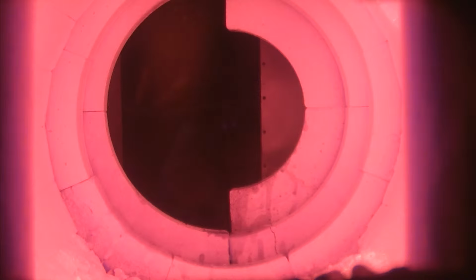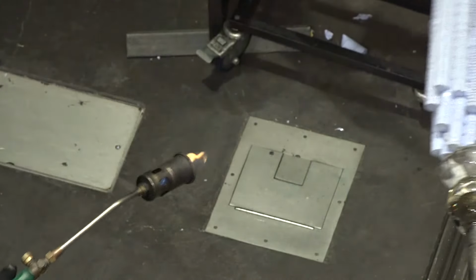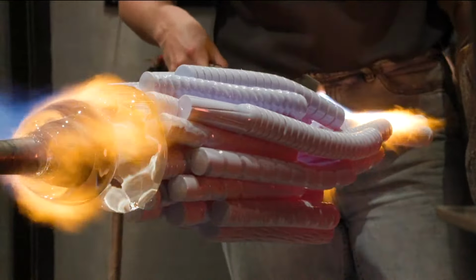So when glass heats up, it expands, and when it cools, it contracts. If it happens really quickly, the glass will crack and break. So if it heats up too quickly or cools down too quickly, stress will form in the glass, and it will come out in the form of cracks. You don't want your glass to crack. And so in order to get these really thick pieces down to room temperature, you have to slowly cool it down. Now, generally, everything must be annealed. Your windows, jars, your pickle jars, your bottles, things like that need to be annealed. Everything does. So some of our standard bowls and vases and pitchers need about a day or so, 12 hours or so, to slowly cool. These pieces need between 3 and 5 days to slowly cool.